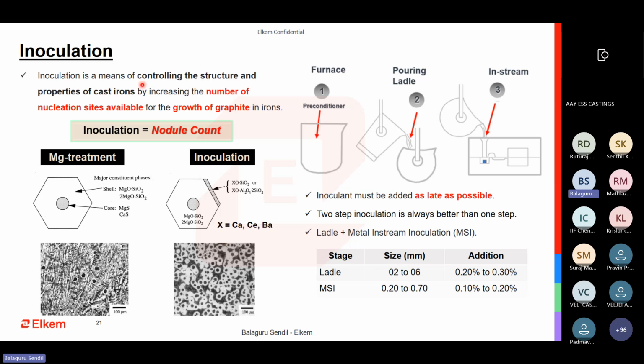Basically, what it does is it controls the structure by increasing the number of nucleating sites. It doesn't create a nucleating site. It increases the number of nucleating sites. Magnesium treatment creates the nucleating site. This is all part of graphite management, whereas inoculation increases the nucleating sites for graphite growth. So inoculation basically gives nodule count.